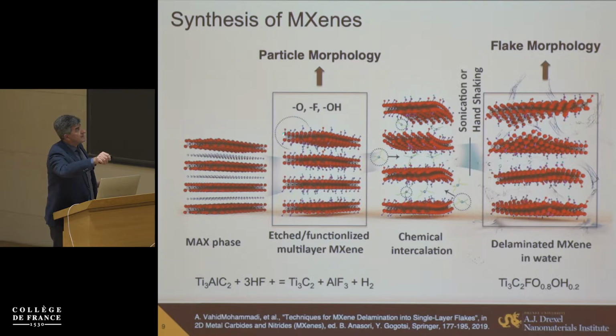So what happens? When we dissolve aluminum, forming fluoride salt, we right away get water or other solvent between the layers. We get formation of salts, and we get protons coming from the acid in between, and we get a structure which is intercalated by ions when surface, because transition metal will not stay non-terminated in aqueous or other active solution.